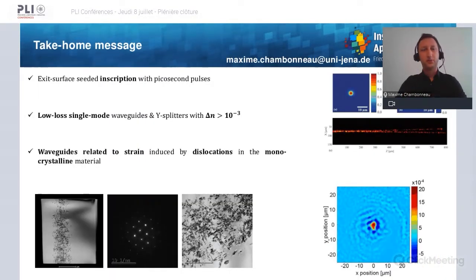So here is the take-home message for this application. We have performed some exit surface seeded inscription with picosecond laser pulses. With this technique, it was possible to inscribe low loss and single mode waveguides and Y splitters with a refractive index change higher than 10 to the minus 3. And the waveguides rely on strain induced by dislocations in the monocrystalline material.